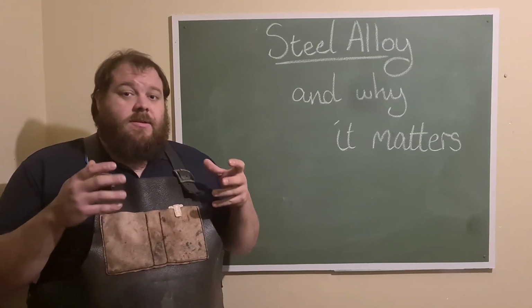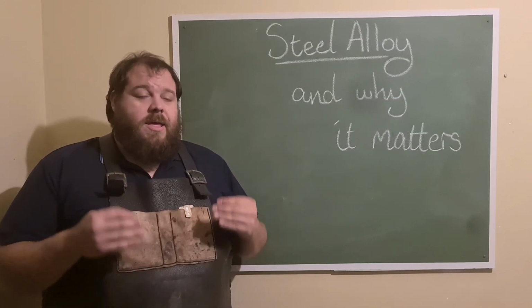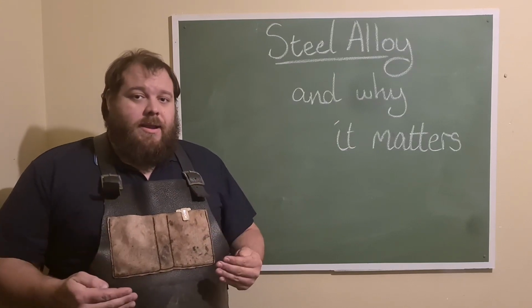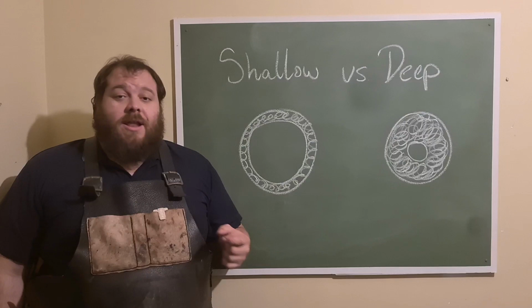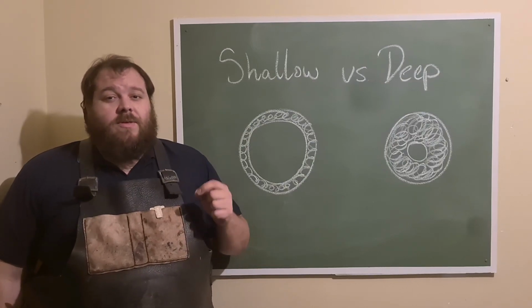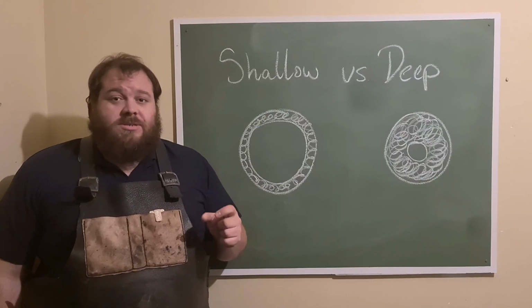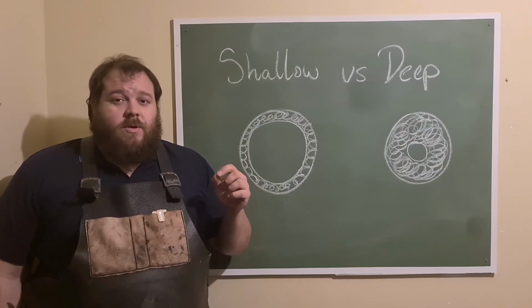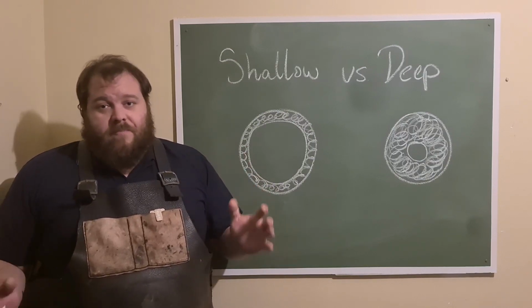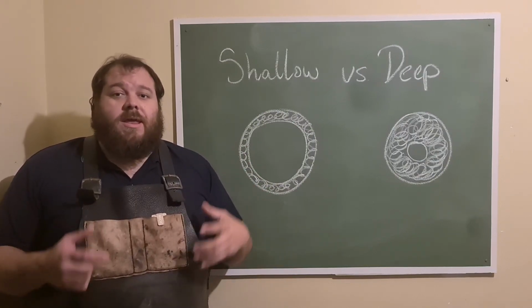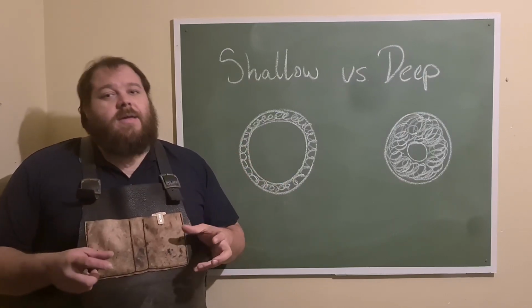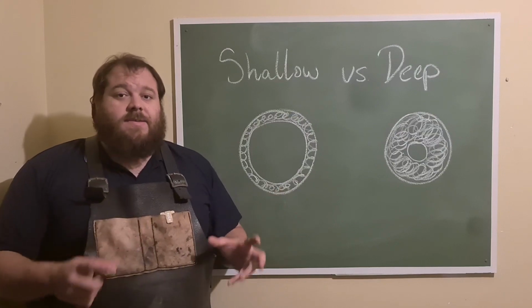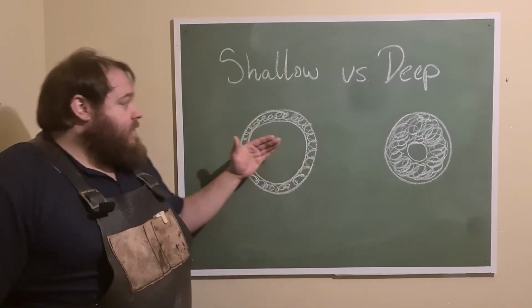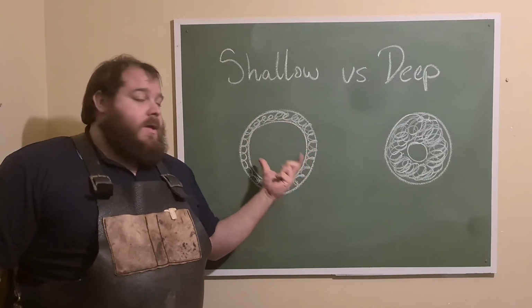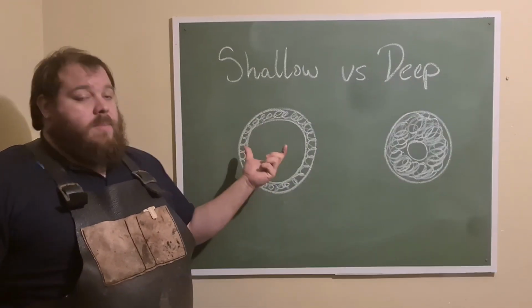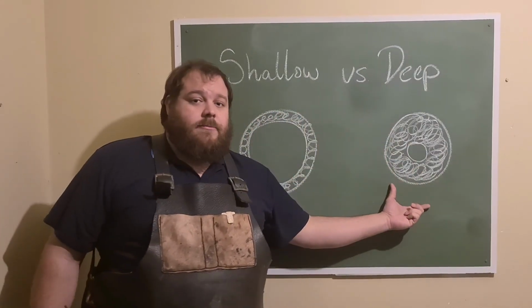And the main reason that specific steel choices are important is because of something called shallow hardening. The key difference between shallow and deep hardening steels is purely the depth at which they harden when quenched in large cross-sections. Metallurgical scientists will take an inch round cross-section or bar of a specific alloy and quench it in a very controlled media. Whatever that media is, they will use the same media for all of the steels that they are testing. And the depth at which martensite forms across the cross-section of that 1 inch round in that media will then determine whether or not it is a shallow or deep hardening steel.